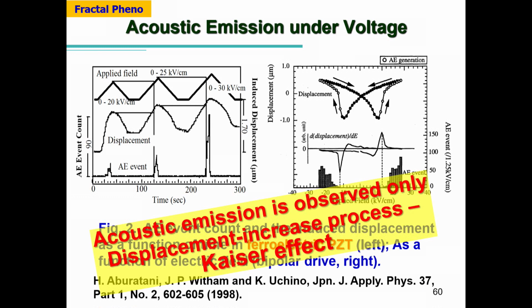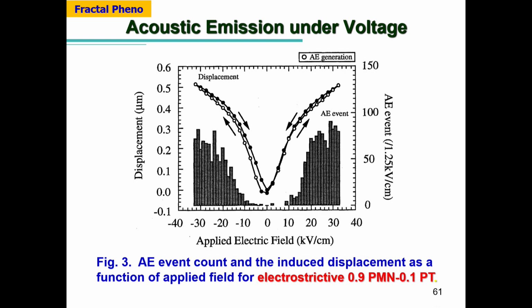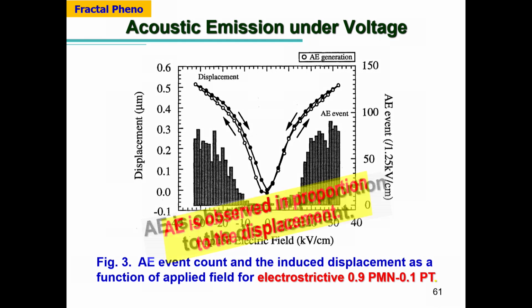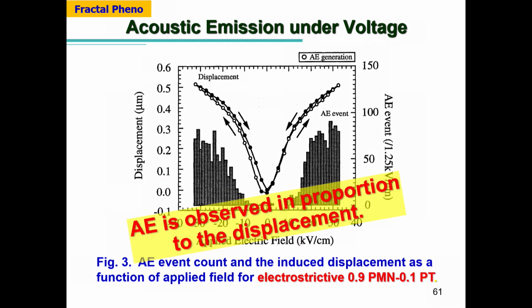And here, at this decreasing point, no acoustic emission. And at the increasing point, you can find the acoustic emission. Okay? So this is usually called the Kaiser effect. In electrostrictive materials, this is intriguing. There is no domain reversal macroscopically, but microscopically, this may work. So this is the displacement curve. Acoustic emission is almost proportional to this displacement curve, okay? So AE is observed in proportion to the displacement.